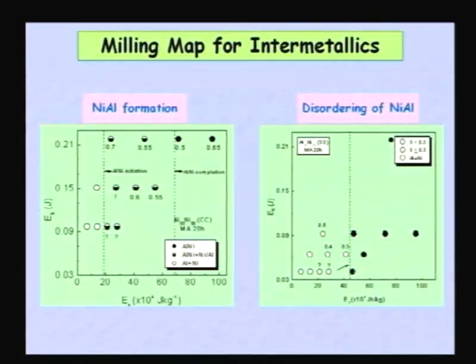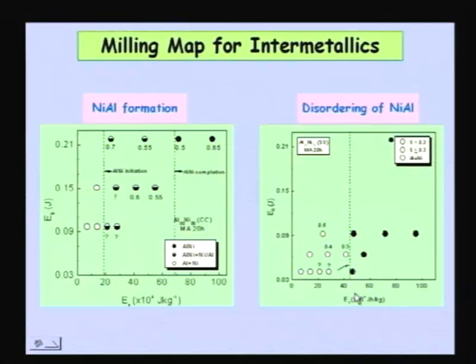So one can do all that, and one can also show that there are milling maps for intermetallics. This is one such intermetallic, NiAl. You can see that irrespective of the impact energy of the ball, there is a minimum total energy where the initiation of the AlNi phase formation occurs, and there is a minimum energy beyond which there is a completion of the reaction. So the reaction starts and reaction completion always occurs beyond a particular energy. Similarly, there is a minimum energy beyond which complete disordering of the ordered NiAl occurs, below which the order parameter is higher than 0, and beyond that the order parameter becomes 0. So suddenly complete disordering occurs, and that is again a function of the energy.